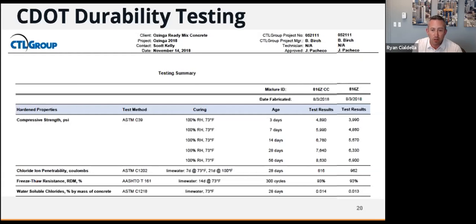As you can see, the strength obviously increased, as Allison mentioned, even with a cement reduction in that mix design. And then jumping over to the chloride ion, you can see that it's actually better than the standard mix, showing that the mix itself is more dense. And some of the reasoning we've been talking about is just because of those nano-sized particles. The concrete matrix itself is denser, therefore not allowing as much to get through the matrix itself. And then obviously freeze thaw on par with the reference mix, and same for the water soluble chloride ions.